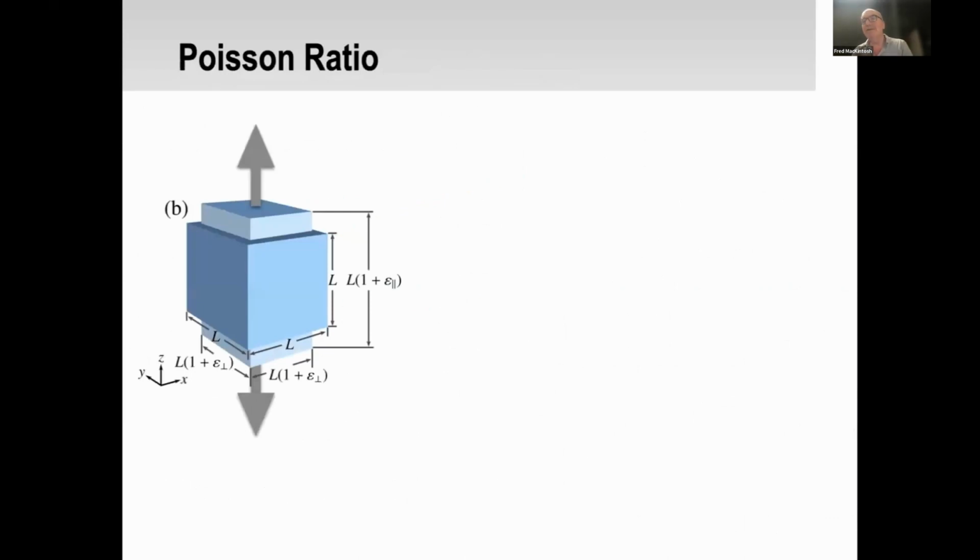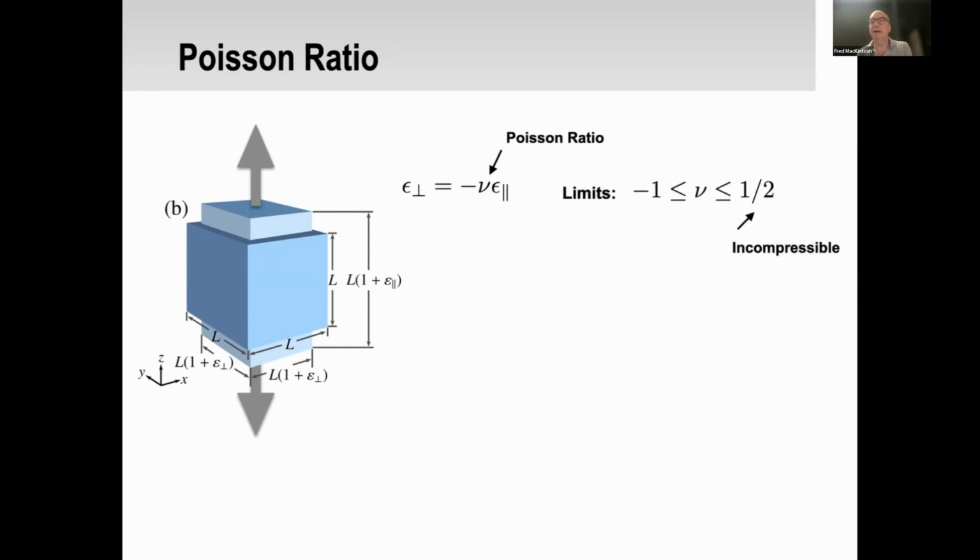So let me turn in the last few minutes to some of the mechanical signatures of this phase transition, consequences of this phase transition. Now, one of these people have looked at quite a bit over the years has to do with the Poisson ratio. So let me just remind you, Poisson ratio tells you about the relationship between transverse strain when a sample is subject to a uniaxial, let's say, extension. If I strain uniaxially by 1%, for a volume preserving system, I would contract correspondingly by 0.5% in each of the two transverse directions in 3 dimensions. That corresponds to a Poisson ratio of 0.5. It's actually an upper bound on that ratio as well,